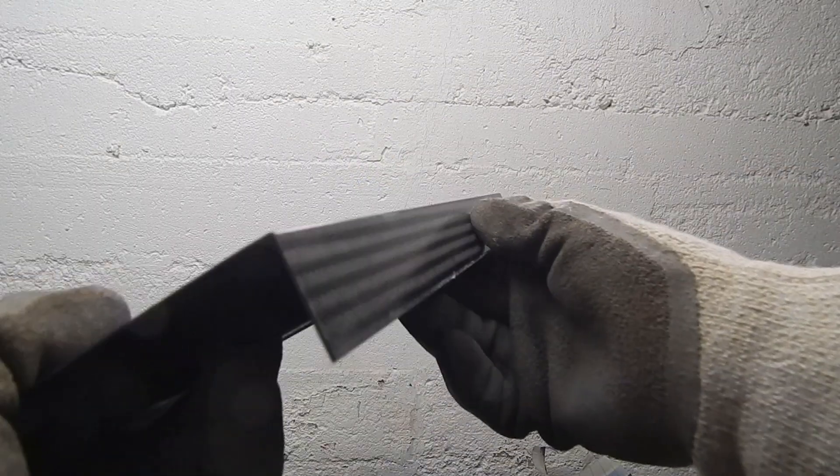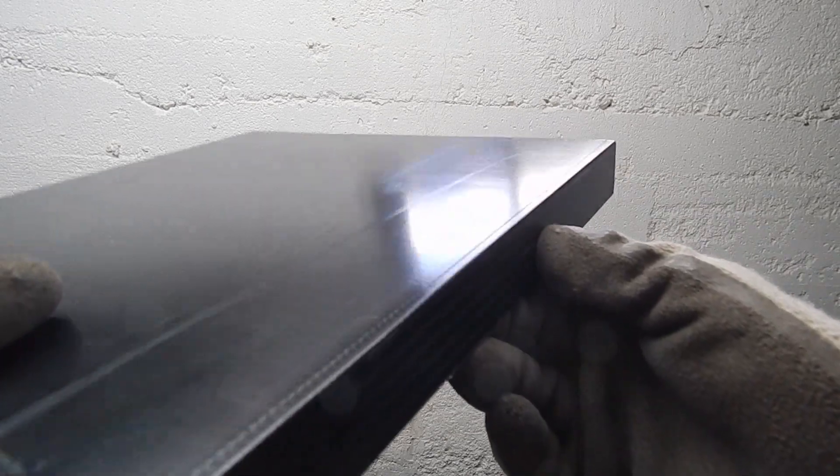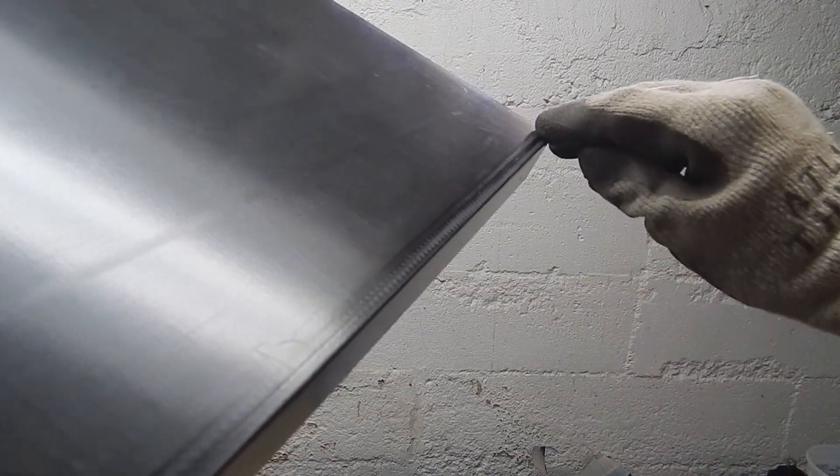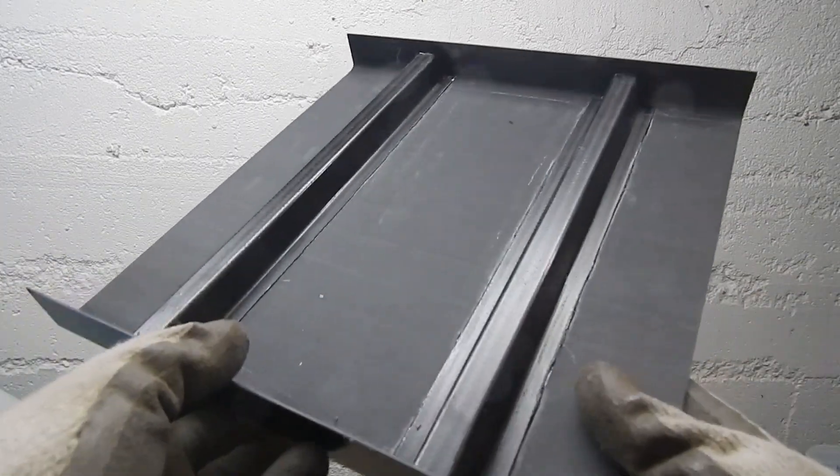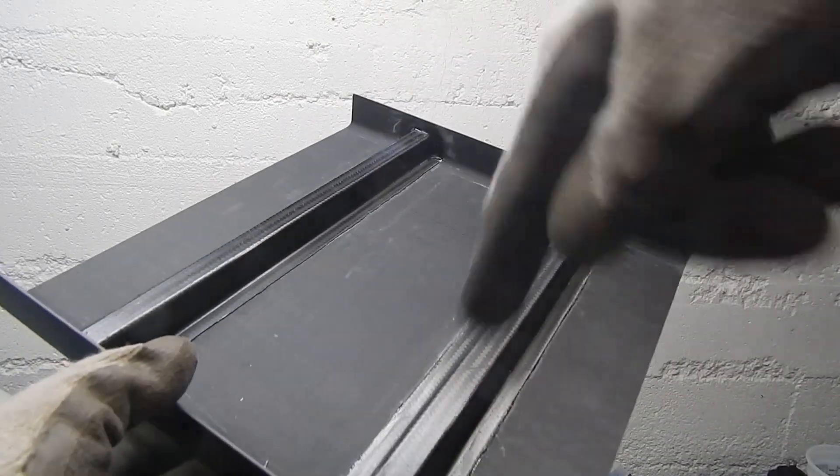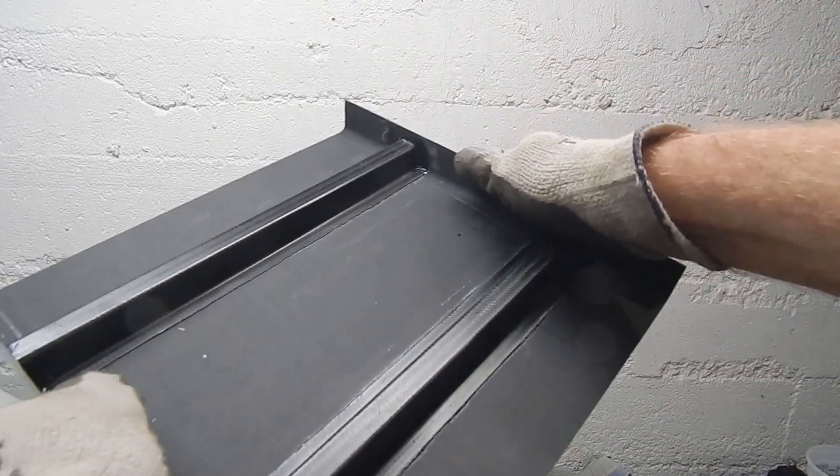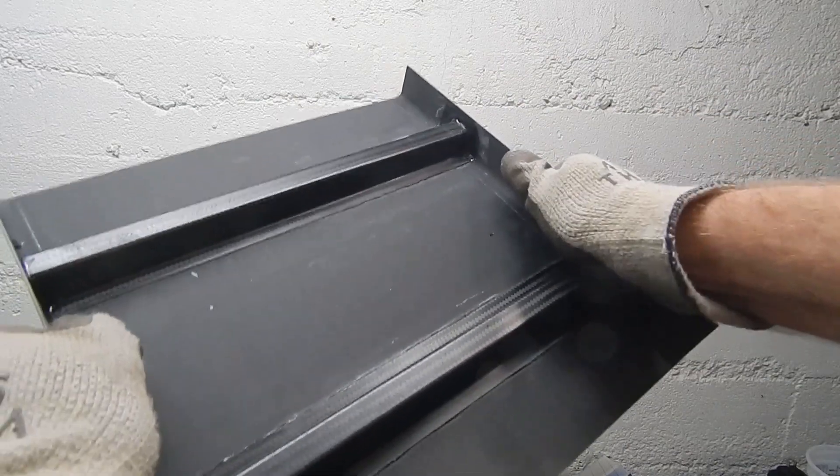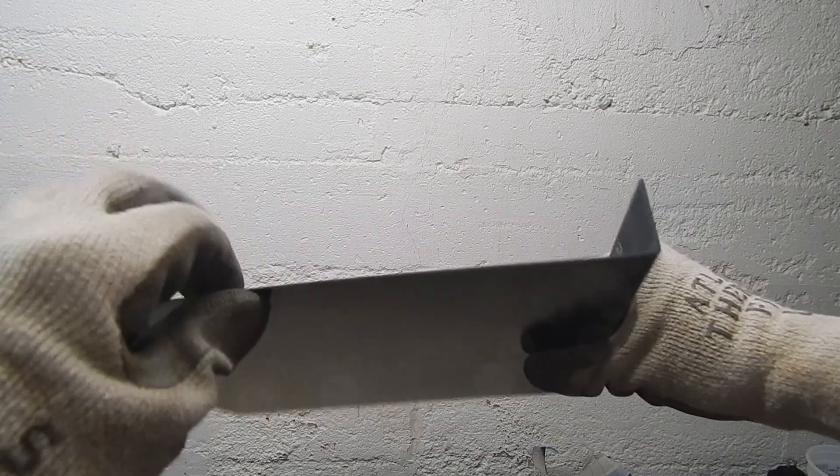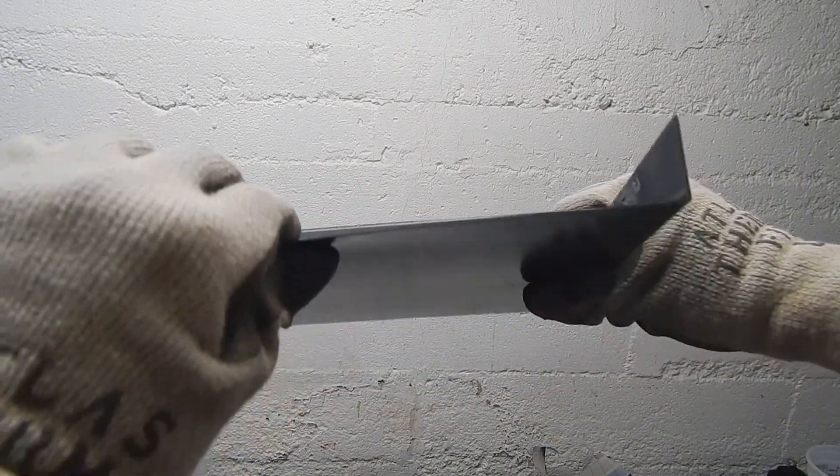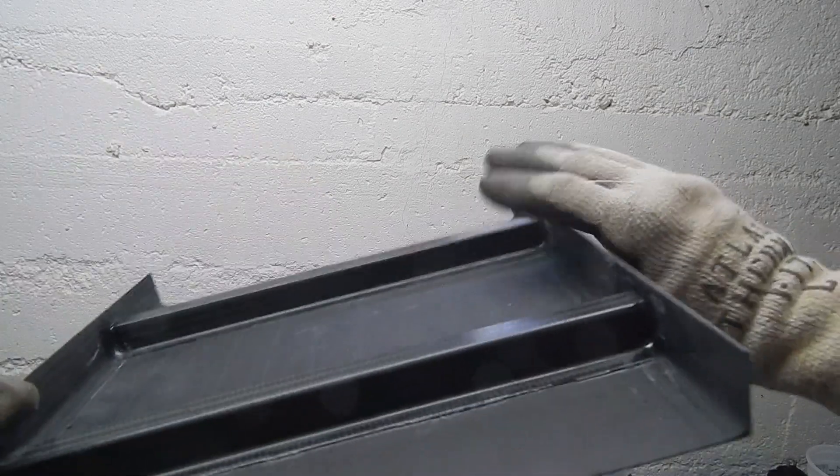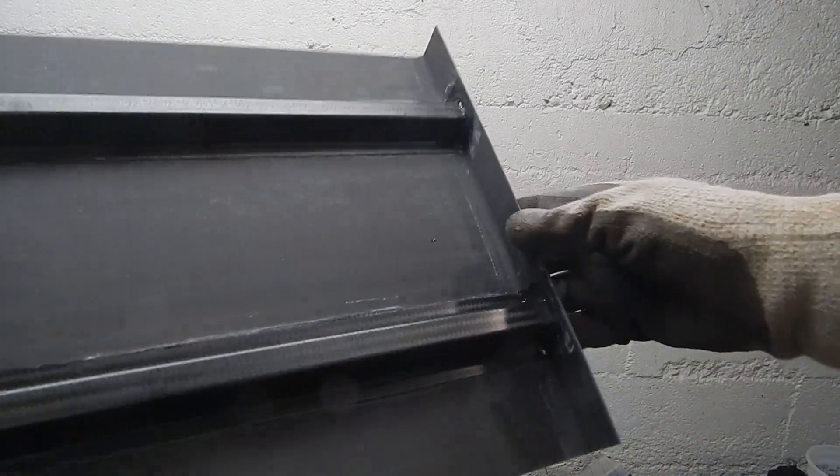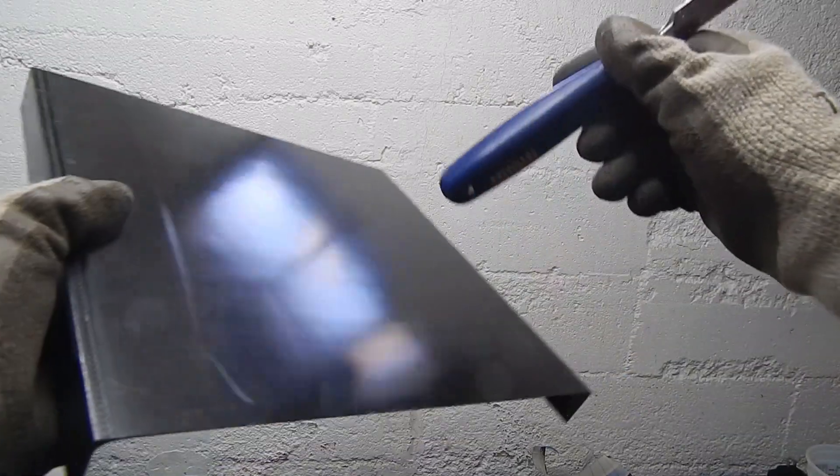So the bottom turned out really nice. The uni looks good. That Teflon leaves a beautiful surface. You can see the sharp corners. There's no voids or air or anything in there. And the woven plus or minus 45 wrapping around the corner. You can see all that extra thickness from the filler strips. It's not that neat. There's some shiny glue, some ugliness there. For something you'd want to be careful to clean up better, mask off better. It's pretty stiff. Surprisingly stiff. Compared to how light it is. And how this one millimeter skin really doesn't feel like much. Where it's unconstrained at the ends, you can bend it easily. But in the middle of the panel, between the stringers there, it's very stiff.